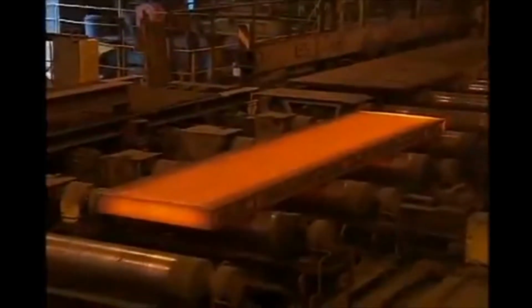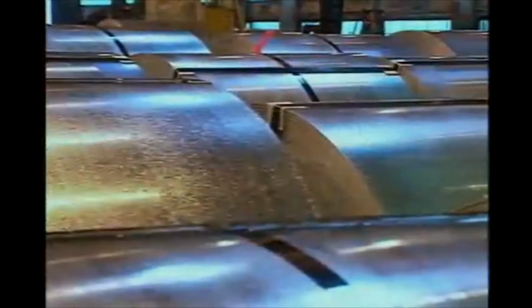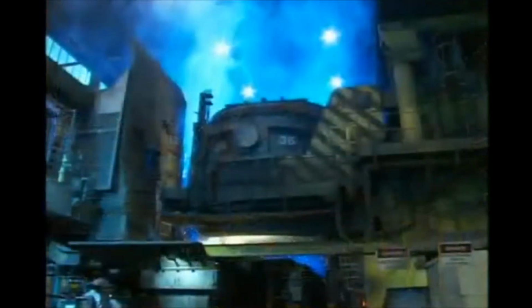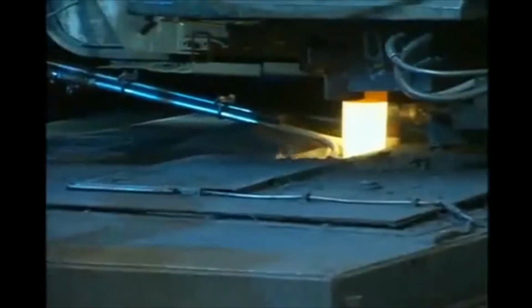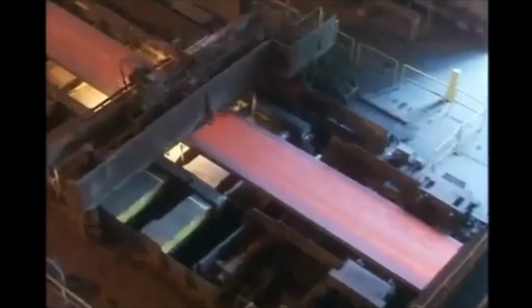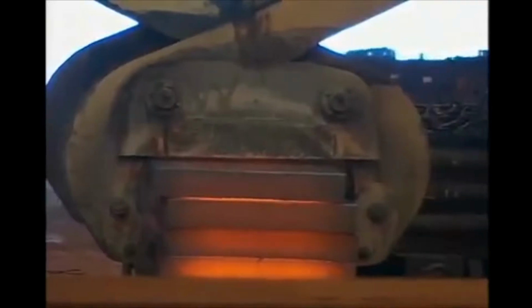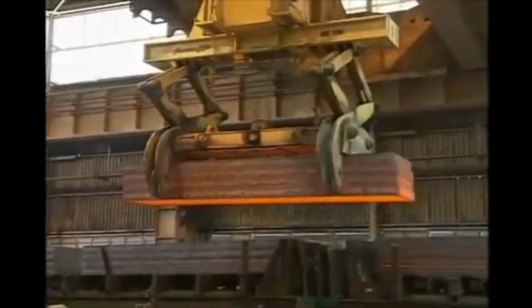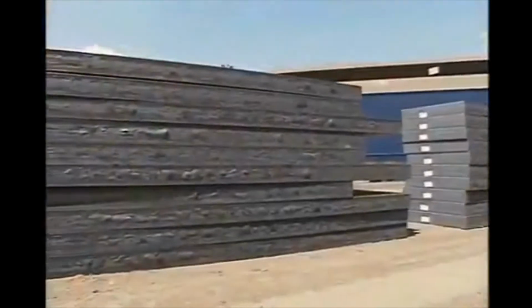The focus then shifts to forming and finishing, which determine even more of the steel's characteristics. The first step in this sequence is to position the ladle above a massive tundish or funnel that feeds a continuous caster containing molds that shape the steel. The molten steel, now at 3,000 degrees Fahrenheit, is channeled from ladle to tundish to caster, where it cools to a red-hot solid. The shape of the mold determines the shape of the semi-finished products that come out of the caster. And since most U.S. steel plants make sheet products, most of our casters output slabs, typically 8 to 9 inches thick and 3 to 5 feet wide. As they exit the caster, slabs are cut into sections up to 40 feet long and stacked to await further processing. Then it's on to the hot strip mill.